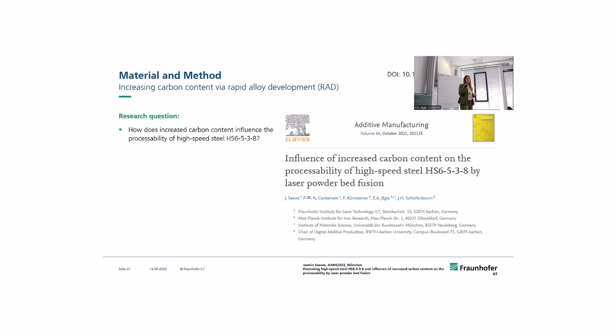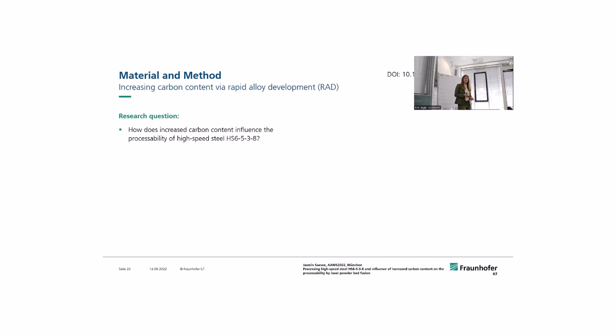Because with a martensite start temperature of about 200 degrees, which would be the one for this steel, it might be the reason why it's cracking. So increasing the carbon content to see if we could prevent cracking. Already saying that it doesn't help, but still it's interesting from a scientific view. And that was a work in collaboration with Philip and Eric of Max Planck Institute.